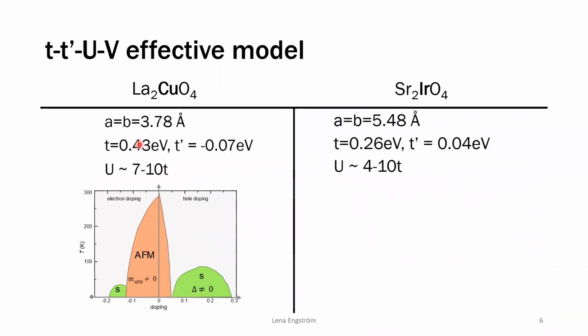So this is the parent compound for a lot of cuprates, and this is the strontium 2 iridium 4, which I am considering. And we just need to know that they have the same structure. There are experiments and some calculations that just compare the band structure close to the Fermi surface. We can just fit these hopping and get some approximation of this U. So you can get these parameters. And then basically with this simplest model, you can just generate this phase diagram.